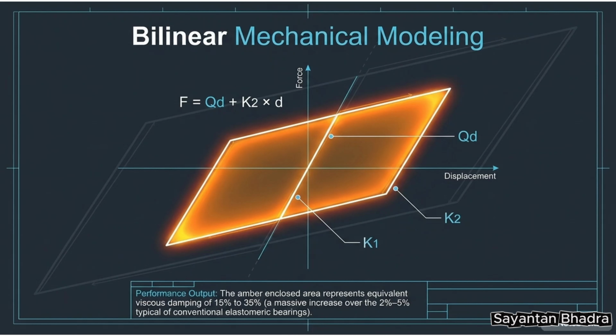Bilinear mechanical model. For nonlinear structural analysis, an LRB is modeled using a bilinear hysteretic relationship defined by initial elastic stiffness K1, post-yield stiffness K2, and characteristic strength QD. The horizontal shear force equation follows F equals QD plus K2 multiplied by D. The enclosed amber area of the hysteresis loop represents energy dissipation per cycle, providing equivalent viscous damping ratios between 15 and 35%.